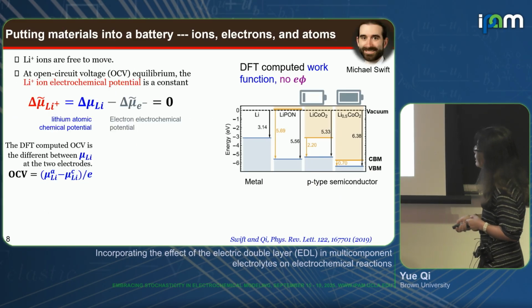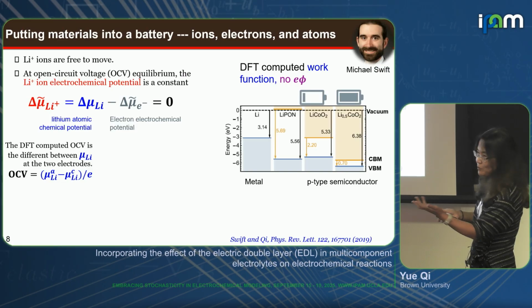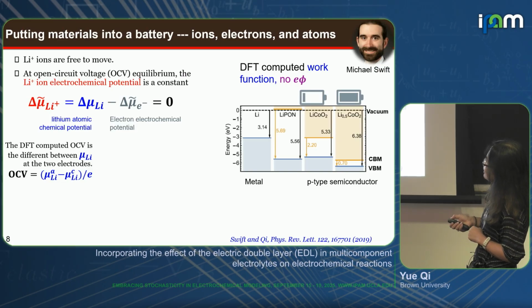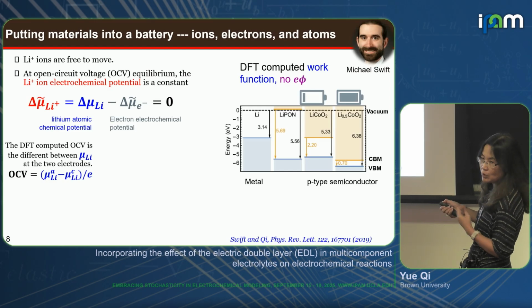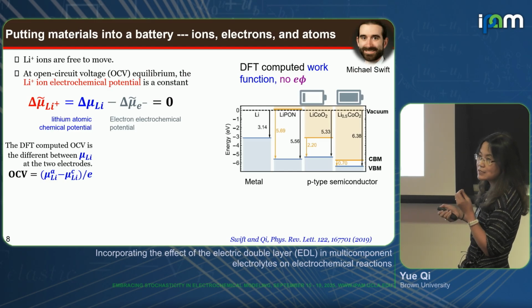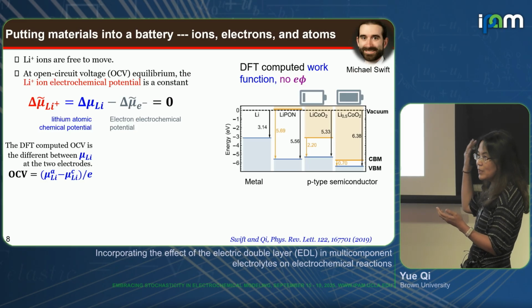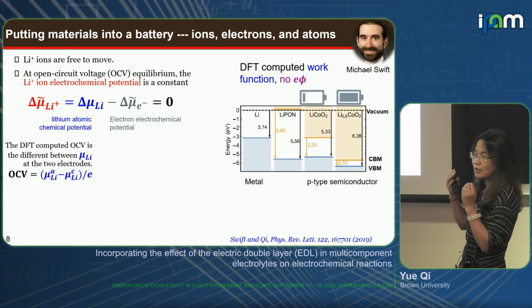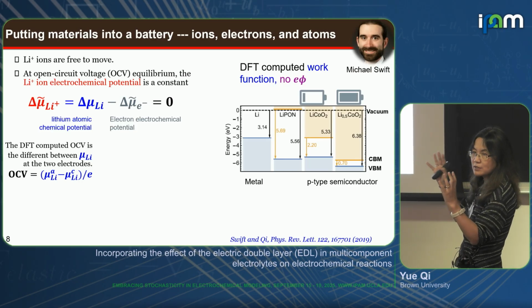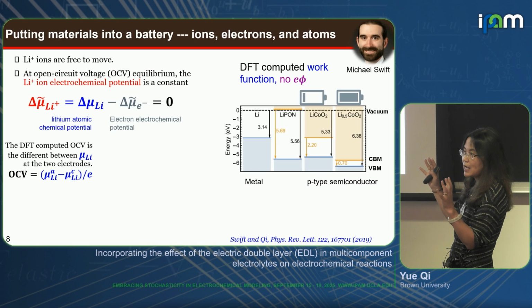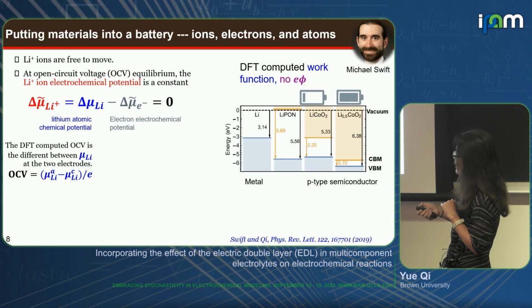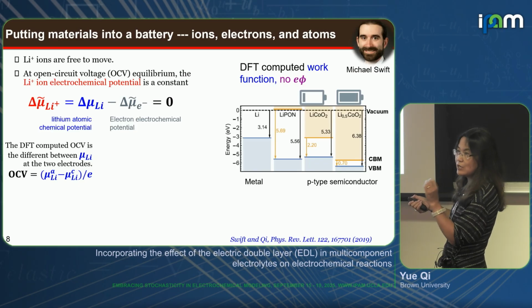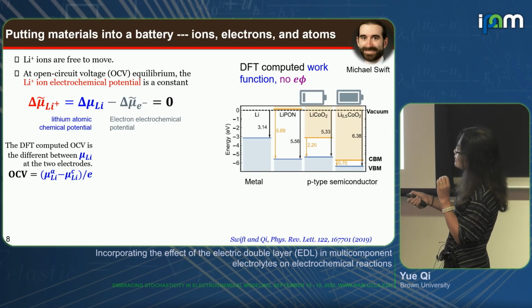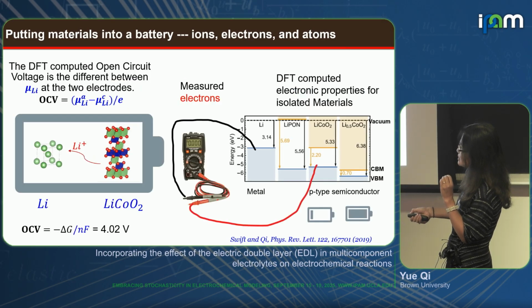Right? And so Michael Swift and I worked a while back in MSU. We just tried to describe this equilibrium condition. The lithium ions need to reach equilibrium because they can move from one electrode through the electrolyte to the other electrode. So when we reach the open circuit condition, the ions have to achieve their equilibrium in terms of the electrochemical potential, and that is related to the chemical potential of the atomic species and the electrons' electrochemical potential. Right? So this we already calculated from our DFT. That's from this is 4.02.